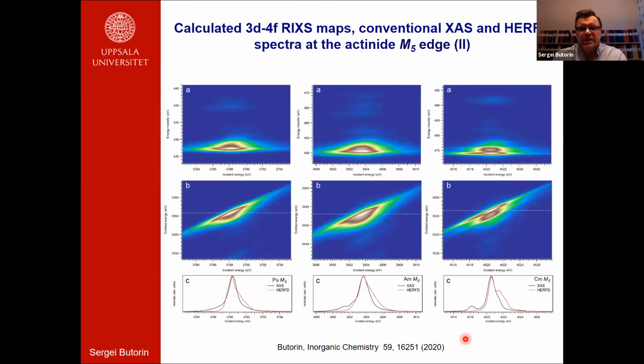Anyway, despite all these differences between HERFD and XAS spectra, one can still use this HERFD technique for studying changes in the chemical state, because for most of the dioxides, the maxima of the HERFD and the XAS spectra actually coincide. So then one could use shifts of the maxima to judge changes of the chemical state, for example, due to covalency.